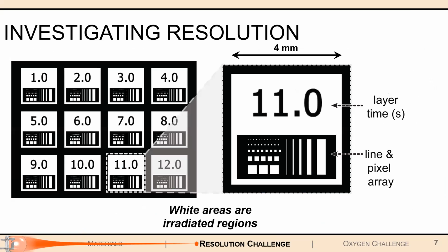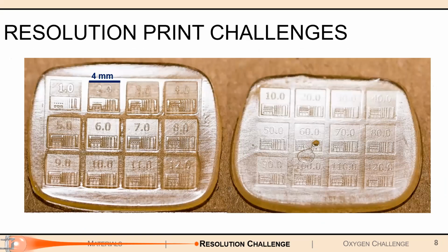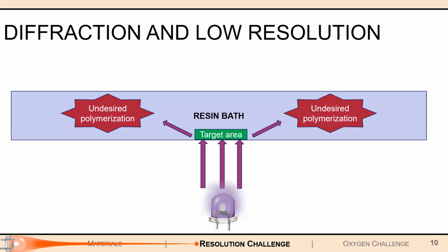Here is an example of a resolution print that we actually use to quantify resolutions. We can see it's pretty rectangular on the outside, and inside the middle we have 12 squares with a number on them. That number corresponds to the number of seconds that layer is exposed to visible light. However, when we actually print this out with our resin, we see that it's rather undefined and blobby on the edge. Resolution is really low. Also, circled in blue, we have some notching in the middle of the print that is known as cure through. The reason this phenomenon is observed is simply because of light diffraction.